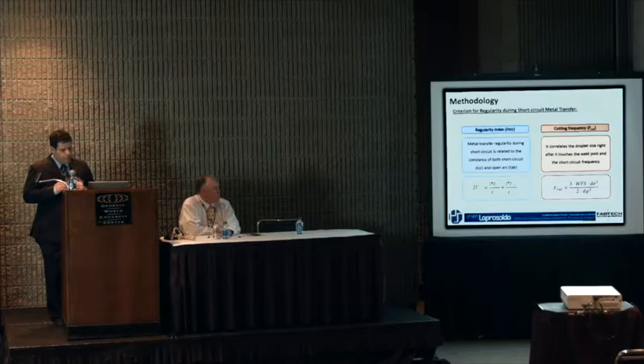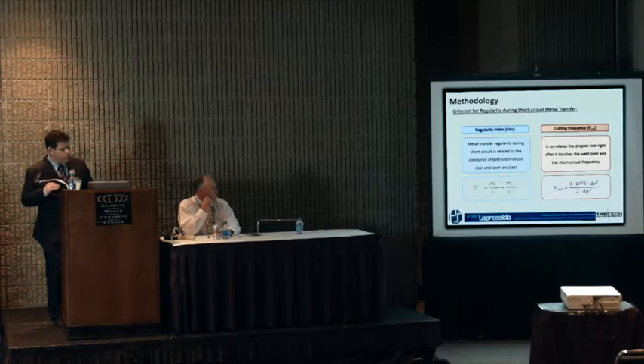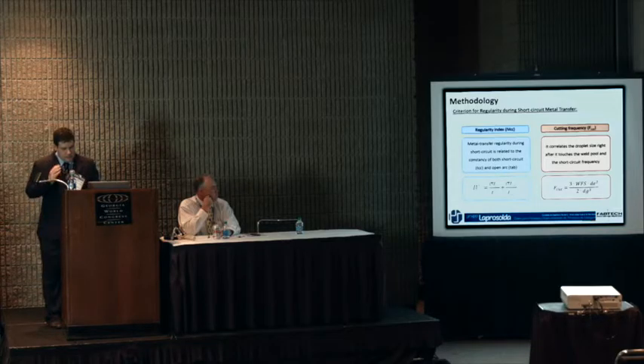So in order to avoid that we reach globular transfer, we just consider a limit for frequency. If you are going to 10 hertz, 5 hertz, 12 hertz, depending on the wire feed speed, droplet diameter, and electrode diameter. So it depends on those parameters. You say, okay, below 10 hertz, I don't consider that short circuit. I am already getting to globular metal transfer. So it's just a frequency to not confound and mix up globular metal transfer and short circuit transfer. It's just a frequency that, below that, I will not consider that transfer as short circuit.